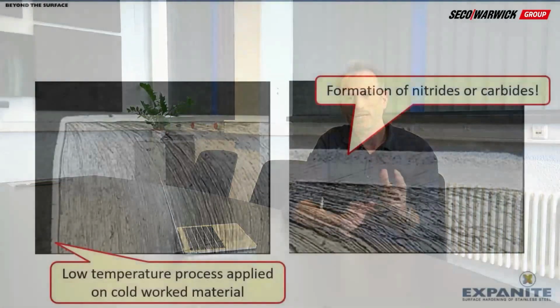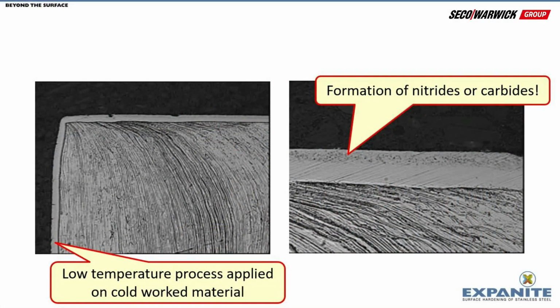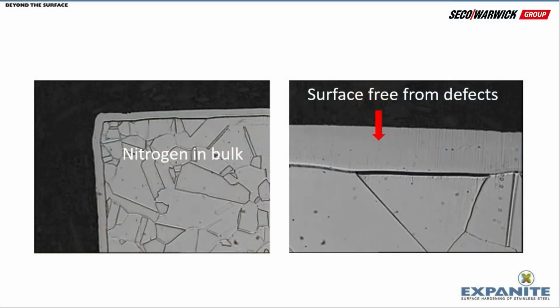The fourth challenge is a challenge that is, for someone, let's say, not quite obvious. For us, it's very important. If we look at a stainless steel part, we look at the surface. The surface is what is important for us. We are making expanded austenite, so we would like the surface to be austenitic. But if you have a component and it has been through a machining shop, you don't have austenite in the surface. You have different things like ferritic, you have delta ferrite, you have martensite, and all those things you need to, let's say, remove to get a nice ground for our process. So the cold worked surfaces is really a big issue, and typically it's more important than the alloy itself.